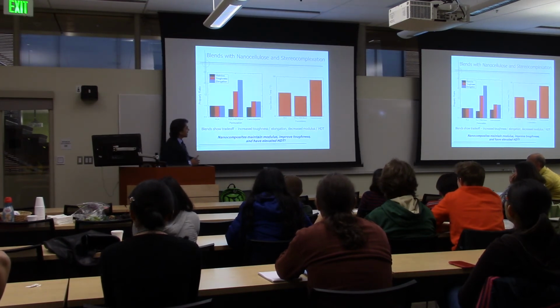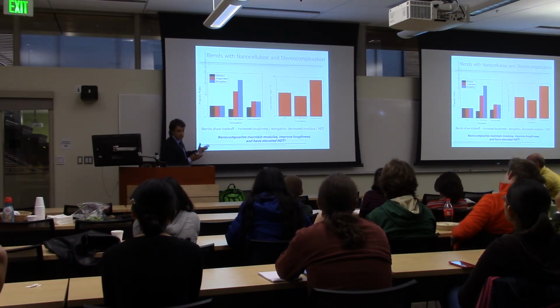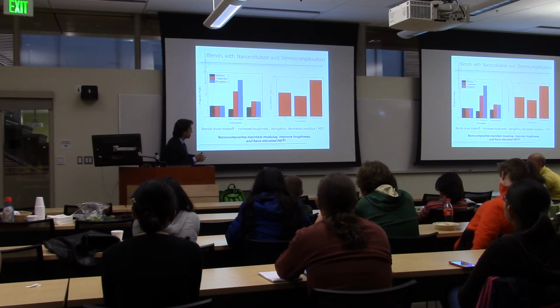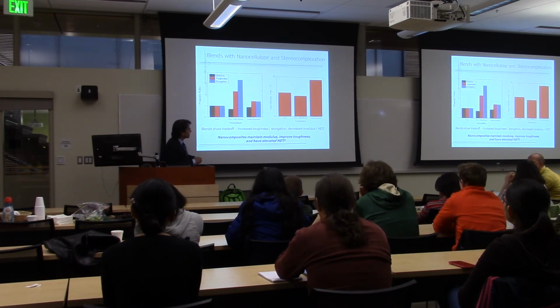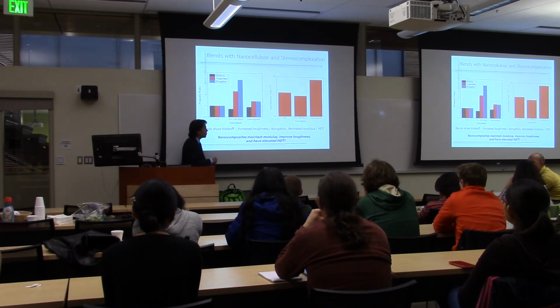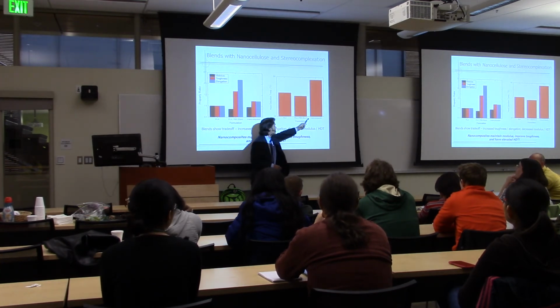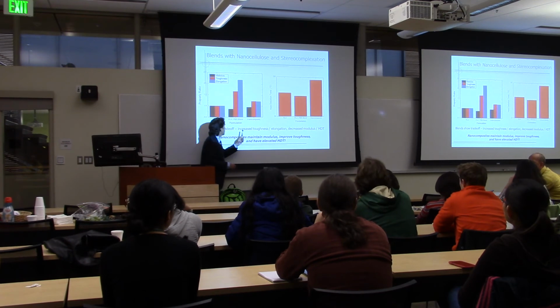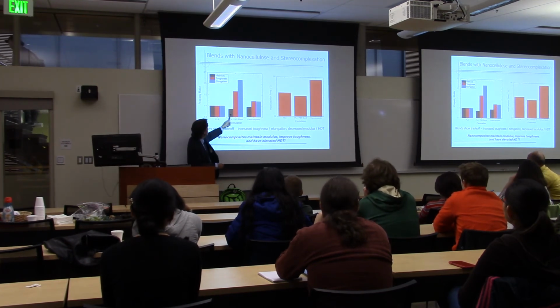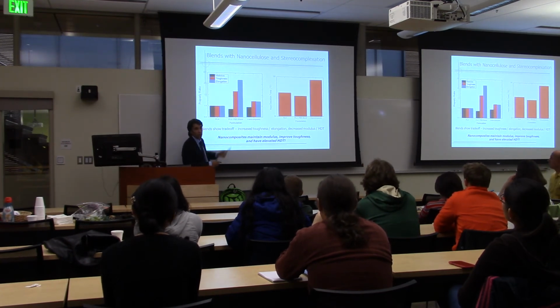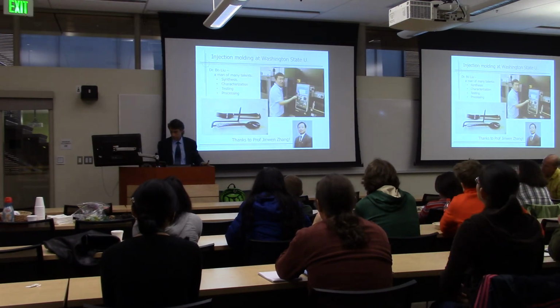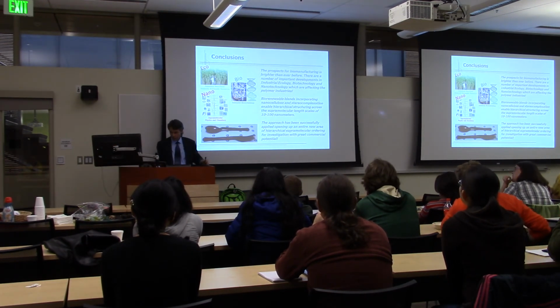Again, the idea here was, can we improve the ductility? Can we improve the toughness of the materials and still maintain the heat distortion temperature? And in fact, we were able to do that. You can see here our heat distortion temperature is higher. We're not quite as good as the blends, but we're better than just PLA. So now we've improved two sets of properties at the same time. We've made plastic forks out of that.